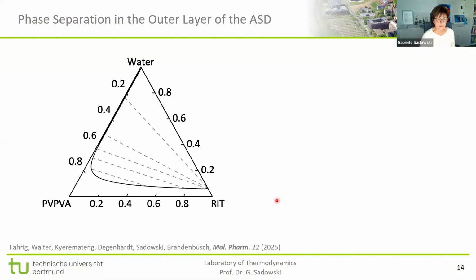So this is the same system. And now, why does demixing sometimes lead to a breakdown in release and sometimes it doesn't? This can be explained on this phase diagram. If we have a small drug load, the smallest we considered was 20%, meaning 0.2, we would start here. The sample is homogeneous, everything is fine. We bring this in contact with liquid water. So that means during dissolution, we move up here. And so we will enter the miscibility gap and, for example, end up here.